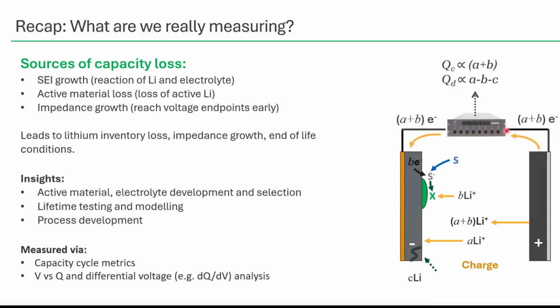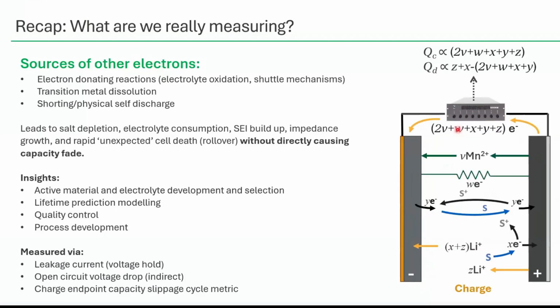But these aren't the only failure mechanisms happening in a cell. They're not the only thing that's contributing to counting electrons through that external circuit. There's all these other types of mechanisms occurring that can be due to electron donating reactions. This is something like electrolyte oxidation or shuttle mechanisms, transition metal dissolution, and even physical self-discharge or shorting.